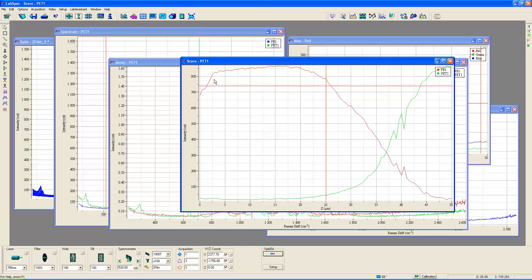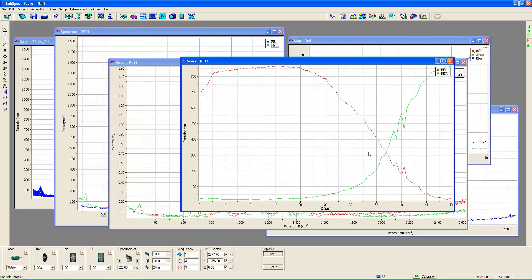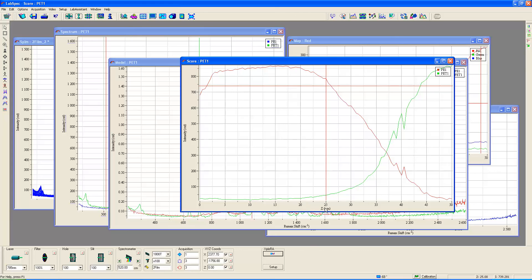I have these plotted normalized so that if we take into account the fact that the beam was perhaps not in focus at the very top and it reached its maximum here at about two, two and a half micrometers, it seems reasonable then that the thickness, the actual thickness of this polymer film is probably going to be approximately in the 35 micrometer regime. Now I said thickness, but remember this accounts for just the stage travel. What we'd really have to do is get the refractive index of the polyethylene and the polyethylene terephthalate in order to convert this axis into a true depth axis for the polymer film.